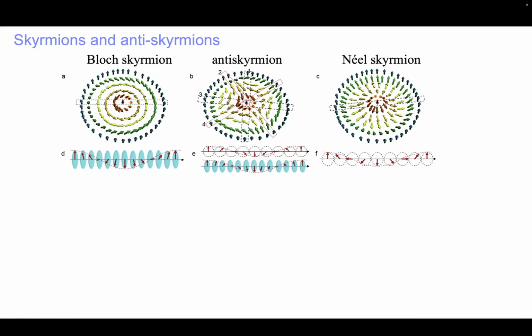And prior to our work, the systems that had been found were something called a Bloch skyrmion. Outside of this Bloch skyrmion, the magnetization is pointing up. In the middle, it points down. And as you go across a radius, the magnetization rotates in a plane perpendicular to the radius as shown here. And the Néel skyrmion is similar to the Néel domain wall I mentioned earlier, in which the magnetization rotates from an up direction outside to the opposite direction inside. And it rotates from up to down along the radius, as shown in this cartoon. These are not cartoons, these are actually micromagnetic simulations we carried out of each of these objects.